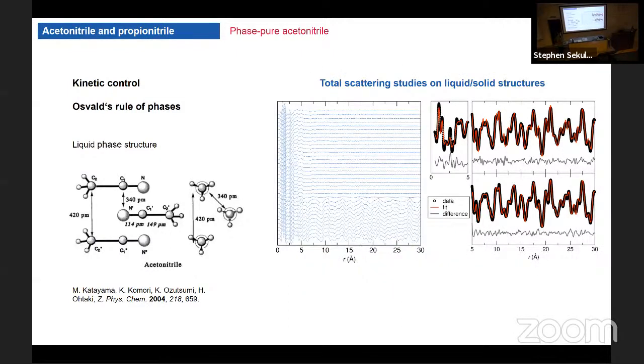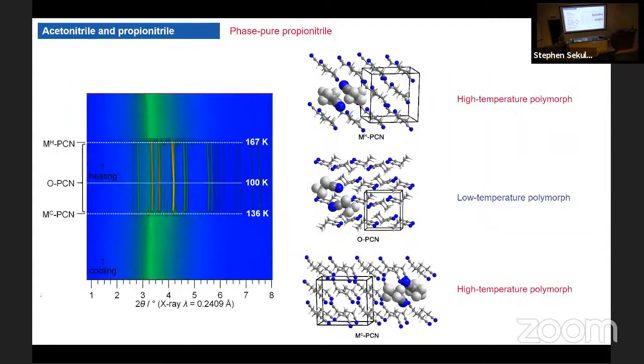We also follow this type of experiments in our lab. What we do is we take total scattering data, and by doing the PDF analysis, pair distribution function, we can figure out the liquid structure of the system as well. Okay, propionitrile now.